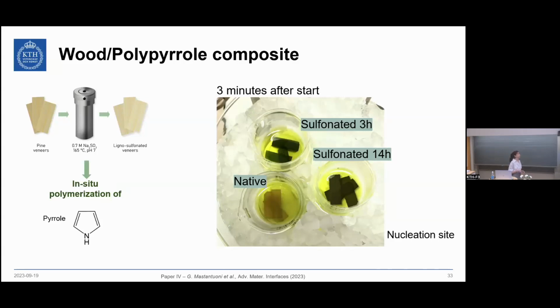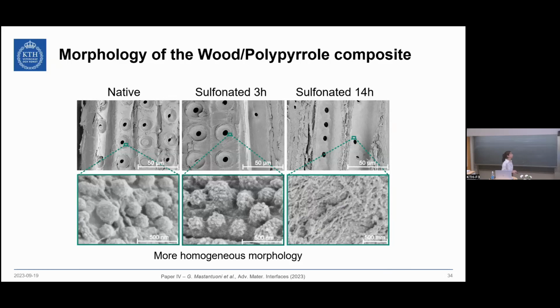The reason for this is that the sulfonic groups can actually act as a nucleation site during the polymerization phase. So here the sulfonation contribution was visible from the very beginning. Furthermore, and this is something we did not expect, the sulfonation also improves the morphology. Here we could see how in the native wood, the polymer was deposited as very coarse nanoparticles, and these nanoparticles become smoother and smoother with longer sulfonation time. So actually, and this was presented in literature as well, the sulfonated groups can act as a stabilizer for the polymer phase and improve its solubility. Here again, an improved morphology also means easier electron transfer and improved electrochemical properties.